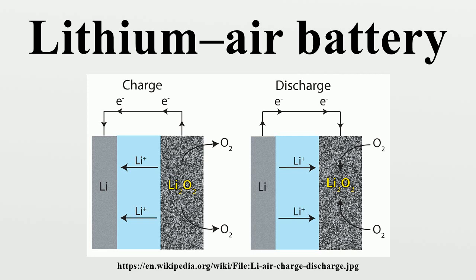Electrochemical. In current cell designs, the charge overpotential is much higher than the discharge overpotential. Significant charge overpotential indicates the presence of secondary reactions. As a result, electrical efficiency is only around 65%. Catalysts such as MnO2, Co, and Pt can potentially reduce the overpotentials, but the effect is poorly understood. Several catalysts improve cathode performance, notably MnO2. The mechanism of improvement is unknown, but may alter the structure of the oxide deposits.